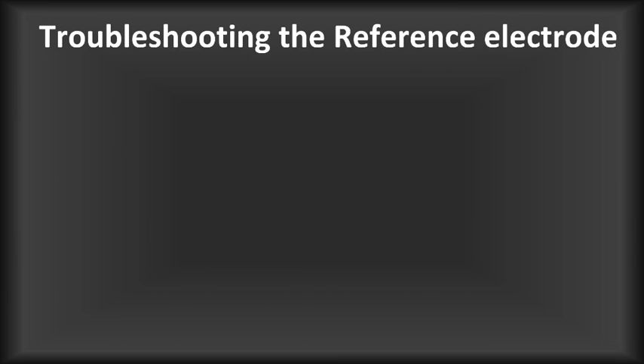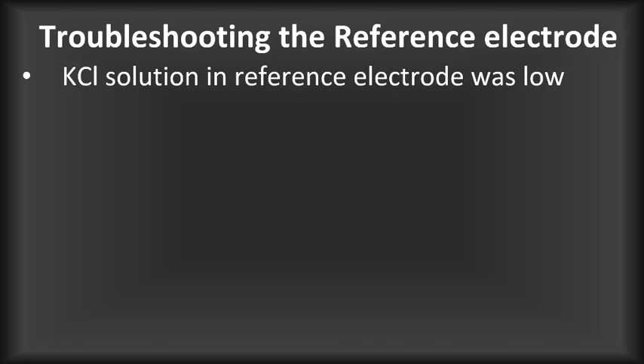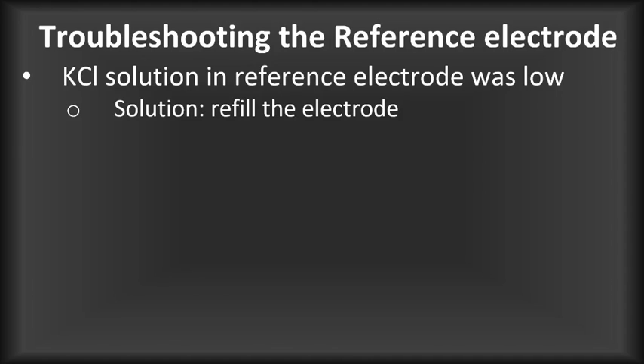So we started with the reference electrode, the silver-silver chloride one. Looking in the little vial that is our reference electrode, we realized that the KCl solution that was inside of it was low. So our solution was simply to refill the electrode. However, we had a bigger problem. A contaminated frit. The frit is the little piece on the end of the vial that actually is in contact and measures the analyte. And so we looked at it, realized it was dirty, so we decided to find a way to see, okay, just how bad is it? And we found that in the user's manual.